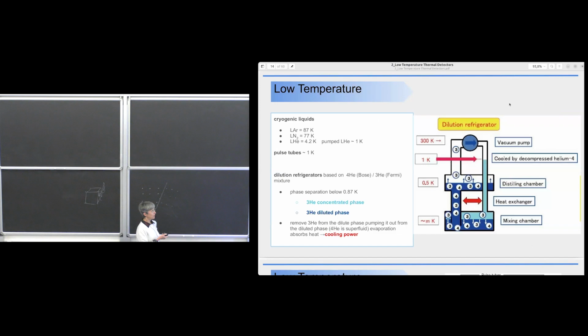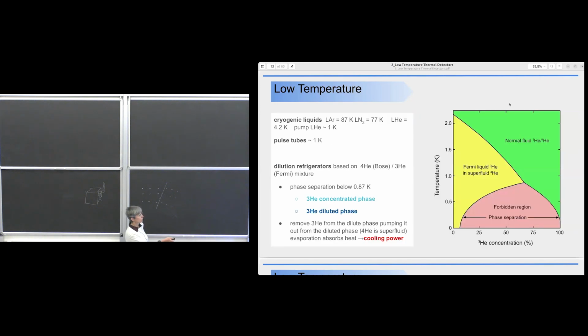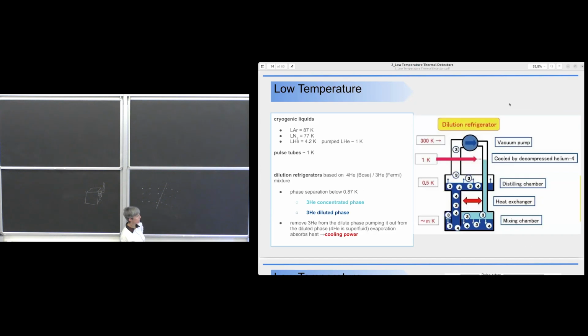you have to start from room temperature, and you have first to go down to the temperature here, that is the temperature where you have the phase separation. And therefore, you have different stages of cooling. Between 300 Kelvin and 1 Kelvin, you cool this mixture using these techniques, either cryogenic liquids or pulse tube. And then you operate your engine, and the fuel, the mixture that is pumped out, cools the mixture that is injected here.